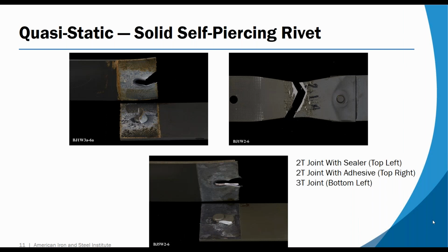This is our first mixed material joint, and this is the solid self-piercing rivet, as I described before. These are the same 3 joints that I showed before, but in each case, the top sheet of 0.7 millimeter bake hardened steel is replaced by 1.2 millimeters of 6000 series aluminum.